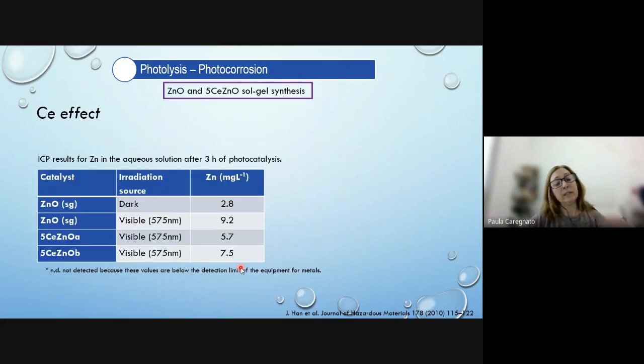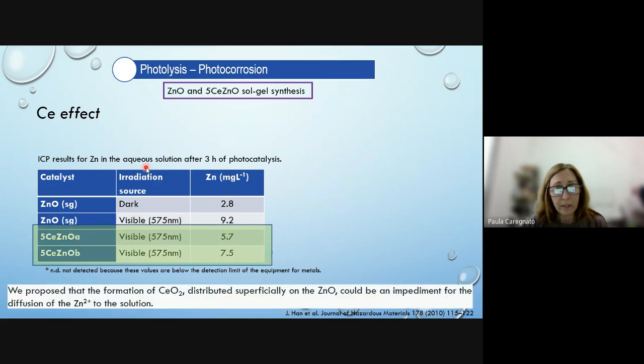So we studied the cerium effect on photocorrosion. We measured the quantity of zinc in the aqueous solution after the 3 hours of photocatalysis. We can see in our results that the zinc content decreased when photocatalysis was performed with cerium-modified solids. So we proposed that the cerium oxide small nanoparticles that were distributed superficially around the zinc oxide could be an impediment for the diffusion of the zinc cations to the solution.